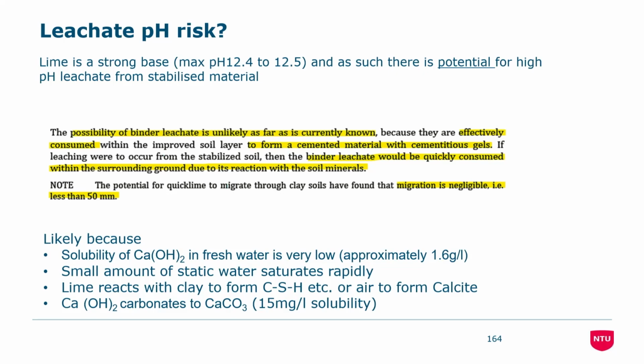Because we're mixing things like lime, this is a strong base, and so it has a pH nominally of between 12.4 and 12.5 at room temperature. So you could say there's a potential for a high pH to leach from that material into a watercourse or some groundwater. So we'll say there's potential, but if you then think of what is known and what is said about this in terms of industry literature and in our British standards, the Earthworks British Standard, which is quoted here, the possibility of the binder leachate is unlikely as currently known because it should form a cemented material within the body and not move too far out of it. And there's this little quote at the end that says the migration should be negligible, less than 50 millimetres. So that's what it says about it.